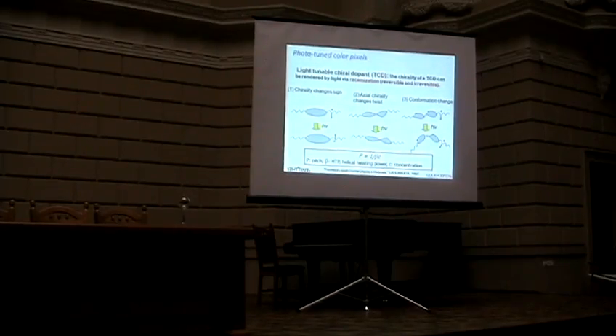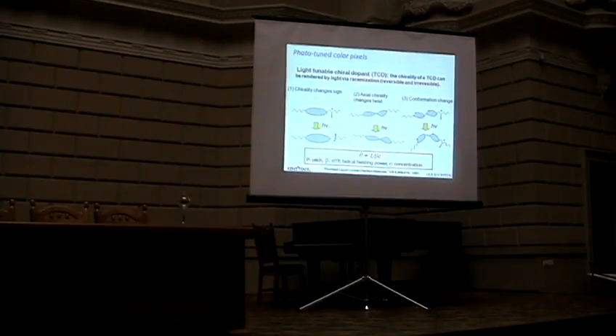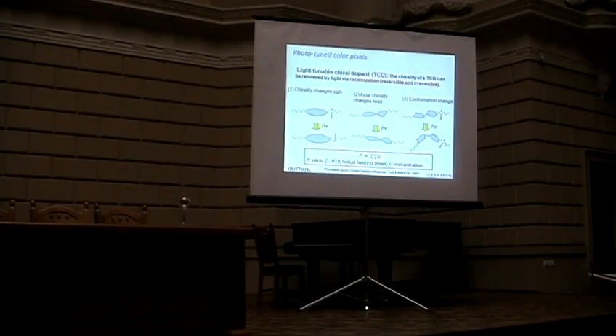People are interested in this type of security sensor device. Here we are showing the use of light to tune the color pixels, and light can be used to adjust the helical pitch. But you need some assistance from an additive, such as a tunable chiral dopant. This tunable chiral dopant should have the ability to change the sign of its chirality, which means that the helical twisting sense of the cholesteric will change from right hand to left hand, or right hand to no chirality. So you lose this chirality and it becomes nematic.